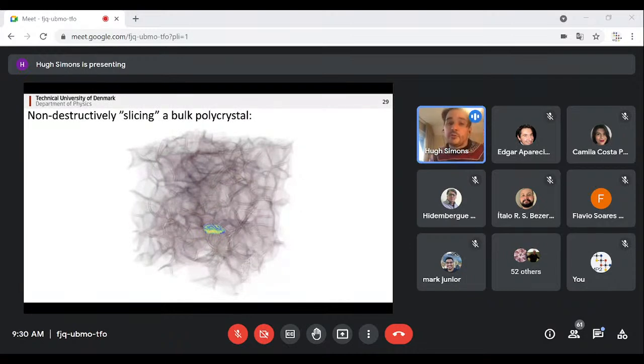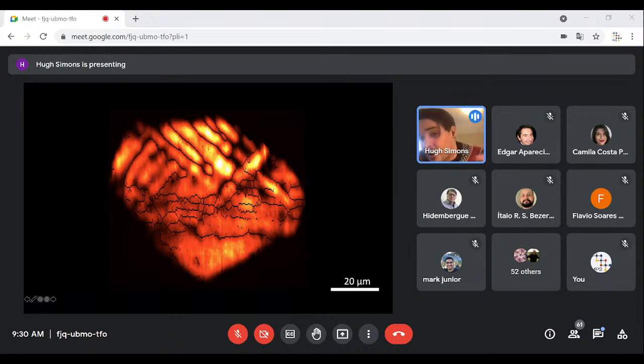And so when we did dark field microscopy on this sample, it's akin to essentially slicing or making a single slice through a single grain very deep inside the bulk. And so with this single grain, we can then visualize, for example, what the strain is. And it's quite beautiful, actually. I mean, you have this ceramic, which can be macroscopically sized. You illuminate it with your X-rays, and then on your detector, you see this beautiful image of just an isolated grain. And this is just one grain of many thousands or millions that are buried inside the sample. It's almost a sort of religious experience. And you see these changes in intensities that come, for example, from the grain boundaries around here, but also the domain boundaries, the domain walls or the twin boundaries that are inside the material.